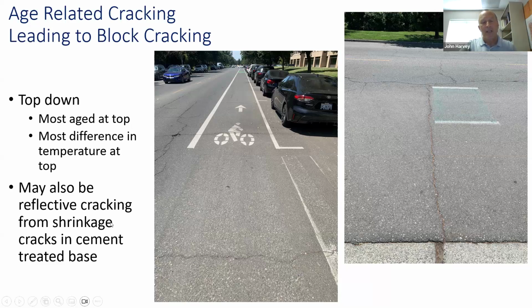Now, if I have existing age-related cracks under the new asphalt, or I have shrinkage cracks in a cement-treated base or something that's been cemented, particularly if the cement content is high, we'll get higher shrinkage. Those will reflect back up.